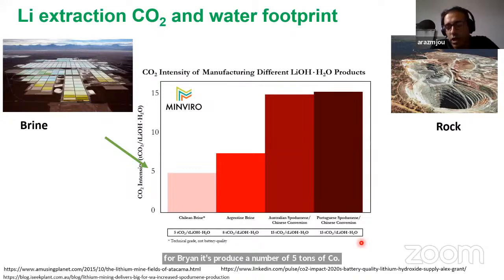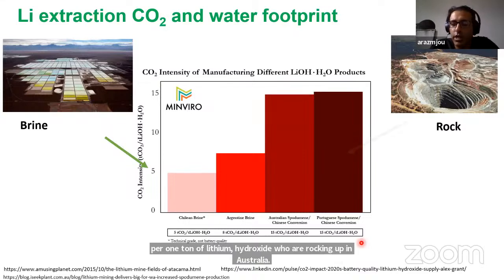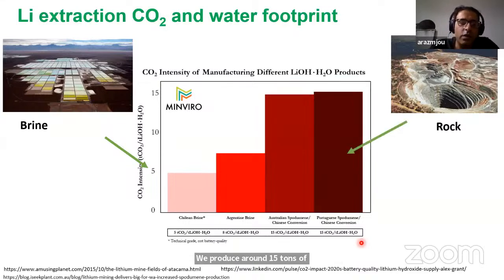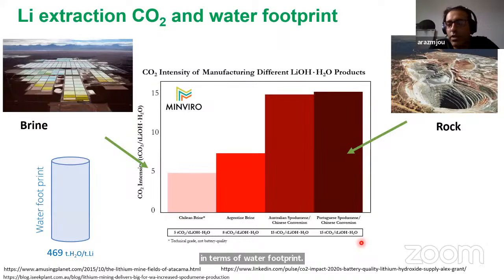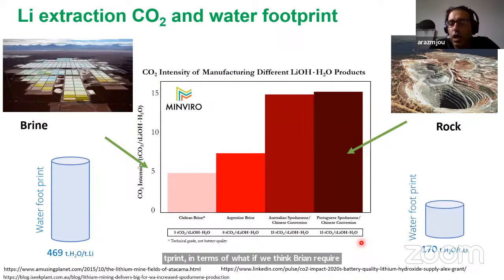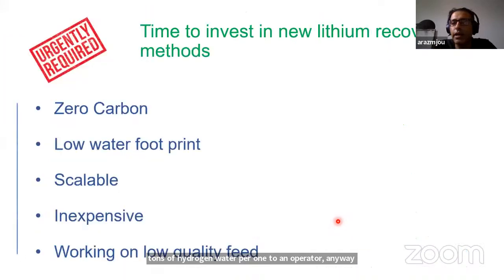For rock in Australia, we produce somewhere around 15 tons of CO2 per 1 ton of lithium hydroxide. In terms of water footprint, brine requires somewhere around 470 tons of water per 1 ton of lithium. And in rock process, it requires 170 tons of water per 1 ton of lithium. Anyway, so you can see there is a significantly